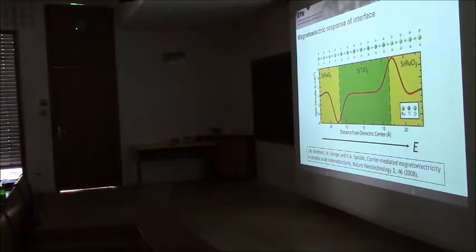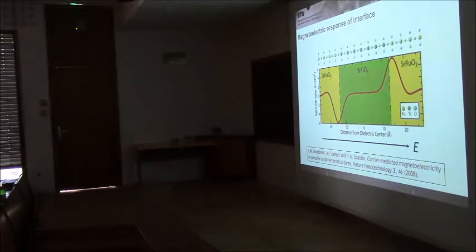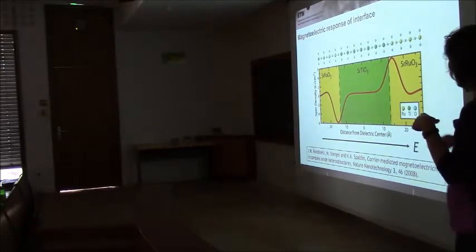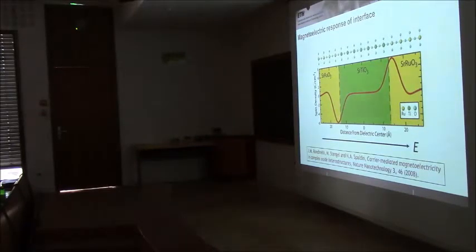And this has been seen. I realize, I'm very sorry, I forgot to put in the experimental data, it's typical theorist. So this has been seen in two systems that I know of. One actually in this system using neutrons by Mike Fitzsimmons at Oak Ridge. He measured explicitly this behavior after we proposed it. And then also in ionic liquids, in basically an electrochemical cell made with an ionic liquid, where the dielectric was an ionic liquid, so they were able to apply extremely large electric fields. Okay, so other questions for that mechanism?